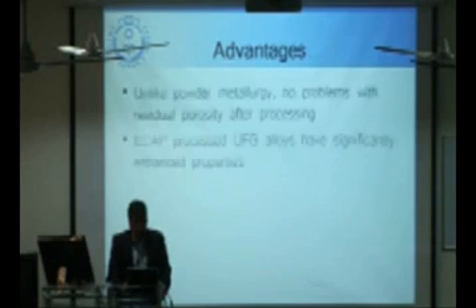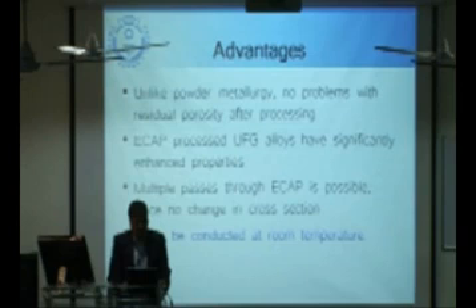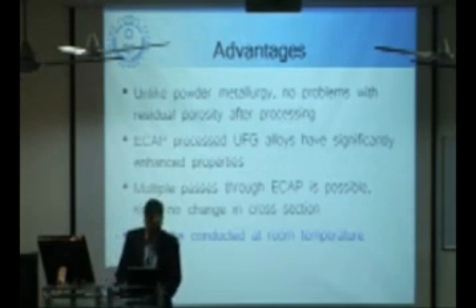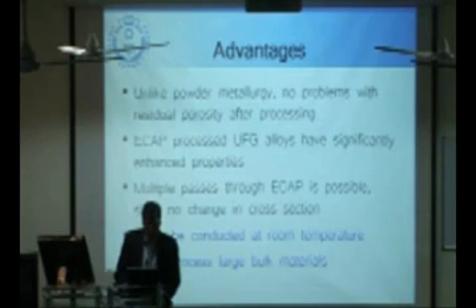The advantages are, unlike powder metallurgy, no problems like in the bottom-up approach, no problems with residual porosity after processing. SPD processed alloys have significantly enhanced properties. Multiple passes through ECAP are possible, since there is no change in cross-section. Multiple passes are not possible in normal plastic deformation techniques. And the most important thing is that it can be conducted at room temperature. And large bulk samples are possible, which is not possible in the bottom-up approach.